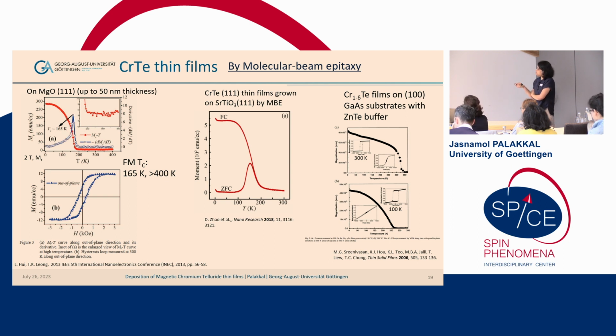But the interesting point is that here you can see the material has a TC around 165 Kelvin, but somehow they also said that this material has a TC above 400 Kelvin. So in my case, I would not believe that this will be a magnetic phase. Here it could be a ferromagnetic short range correlation or something. But they measured the out of plane MH hysteresis loop and found a convincing MH curve. And they suggested that this material is a high temperature ferromagnet. And in this work also you can see the magnetic moment is not completely zero.